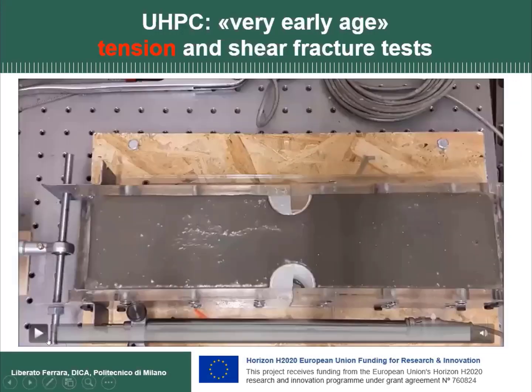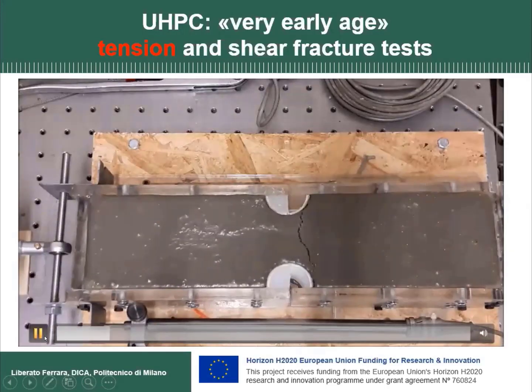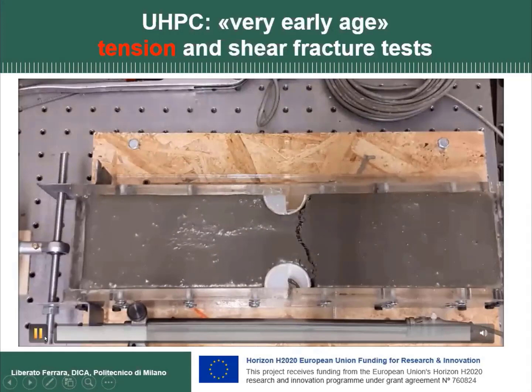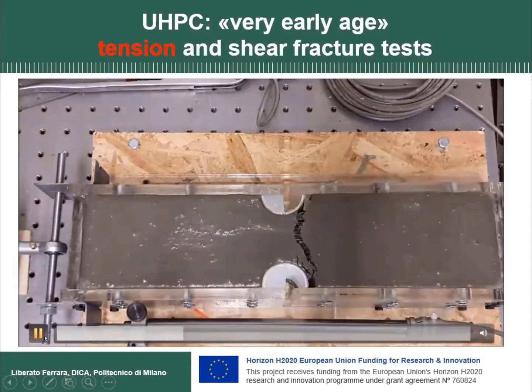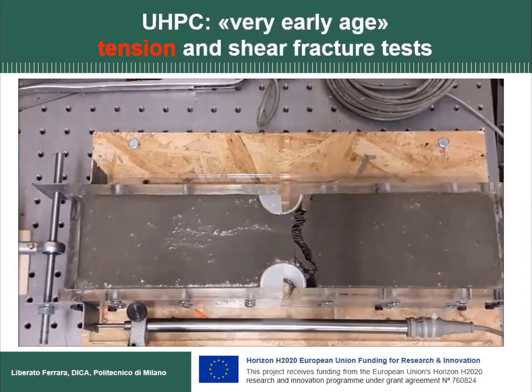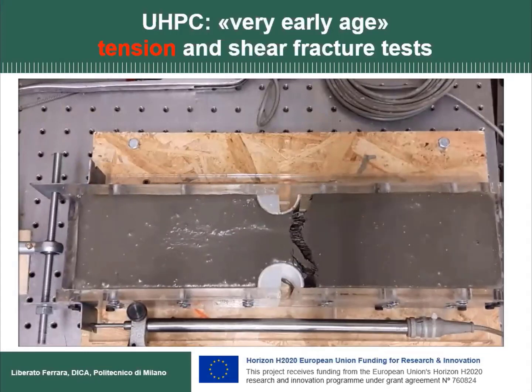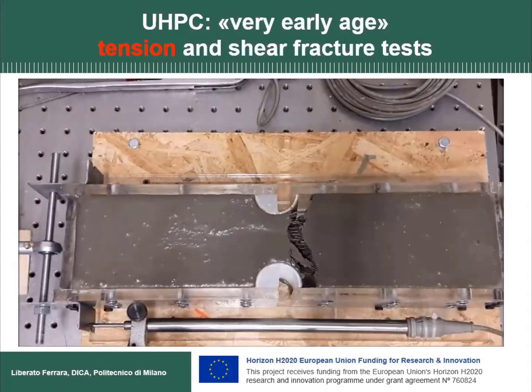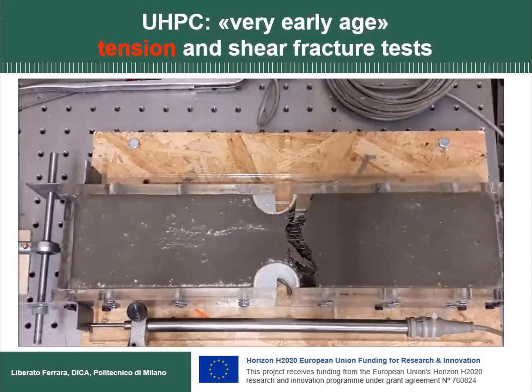Here is a short movie. This is a tensile fracture test at about 2 hours. We fill the mold, we poured the mix from one side, and you can see the fibers were very well aligned in the direction of the tensile force.